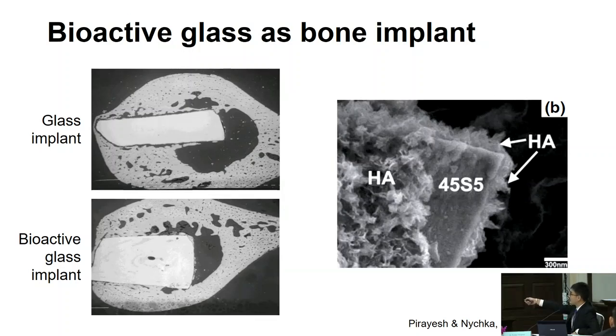So this piece is a glass implant. It is an untreated glass surface, and this is the bone. You see the gap between this glass implant and the bone, and this gap is actually the fibrous encapsulation. It means that the bone tries to reject the glass implant. But when we change the composition from normal glass to bioactive glass, which incorporates calcium into it, you can see that the gap is very minimal. We cannot see the gap here now.